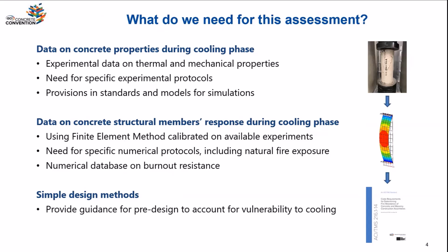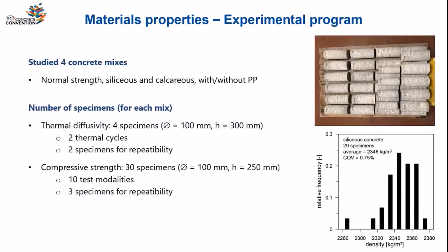And with that, we can collect data on burnout resistance, which I'm going to define in a moment, and then look at simple methods or pre-designed tables that would give provisions for addressing the vulnerability to the cooling phase for achieving burnout resistance. So in the first phase, we started with the experiments and collecting those material properties. We looked at different concrete mixes. We designed two types of tests. So the first types focused on the thermal properties. We wanted to measure thermal diffusivity during heating and cooling. And then we also looked at compressive strengths.